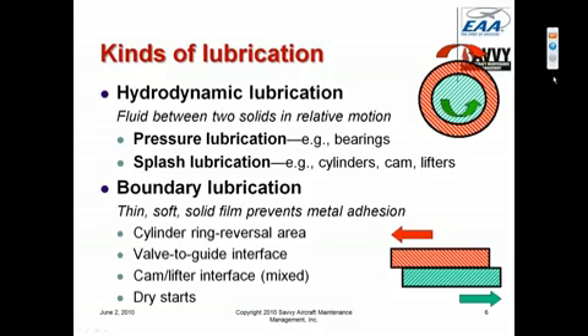Another area where we rely on boundary lubrication is the valve guide, the valve stem to valve guide interface, particularly for exhaust valves, because we've got moving parts in there, the stem and the valve guide, that have essentially no hydrodynamic lubrication, both because they're not moving fast enough and because there's almost no liquid oil in the stem to guide interface, simply because it's so hot that liquid oil in there would coke and not be able to provide any kind of effective hydrodynamic lubrication. So we rely mainly on boundary lubrication provided by various oil additives to keep valve stem and valve guide wear to a minimum.